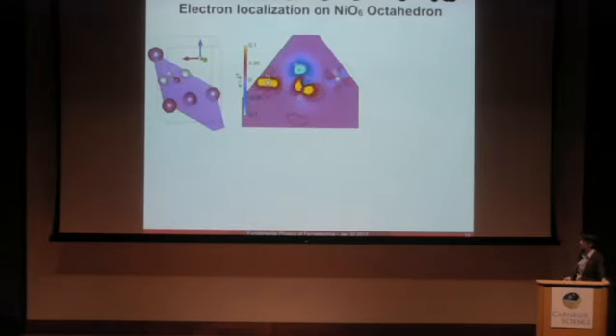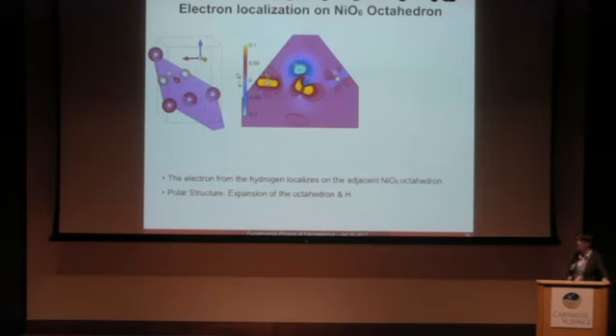So we can actually easily visualize this electron localization by comparing the charge densities of different calculations. And so we can see that there is an electron depletion around the hydrogen, and it accumulates on this nickel-oxygen octahedra neighboring it. So here I'm showing a contour plot that's along the 1-1-1 plane that pretty much cuts along this hydrogen-oxygen bond. So the electron is localizing on the nickel-oxygen octahedra. It's not just on the nickel alone. And we get a polar structure that is not just due to the position of the hydrogen. We also have an expansion of the associated nickel octahedra.